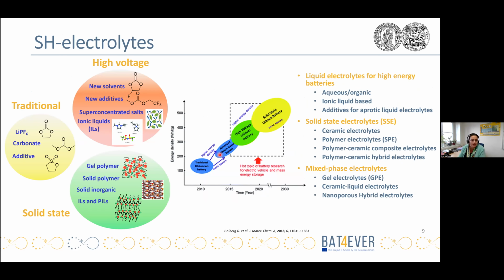Let us now look more closely at the design of self-healing polymer electrolytes. As we said, we have the ability to embed a liquid component like ionic liquid physically into the polymer matrix and gain the gel electrolytes. Here, the polymer component is increasing the mechanical stability to a distinct extent, whereas the liquid component is staying more or less mobile and is able to increase the ion conductivity of the electrolyte. In the solid electrolytes, we have increased mechanical stability, but at the cost of the ion conductivity. However, the polymer electrolytes can be damaged, and the introduction of the self-healing functionality can increase the lifetime of the battery.